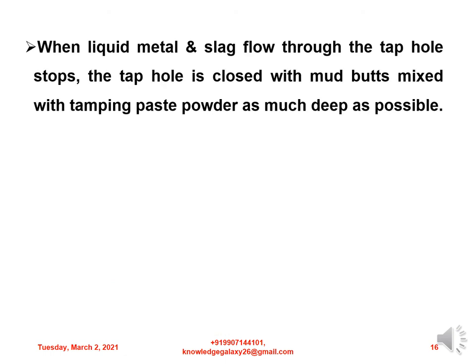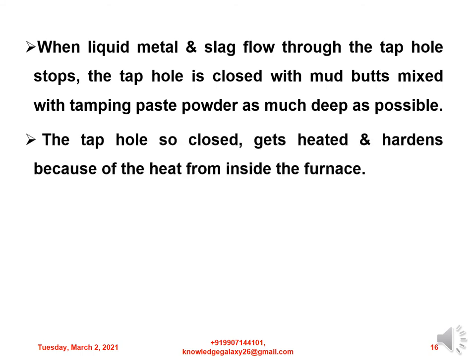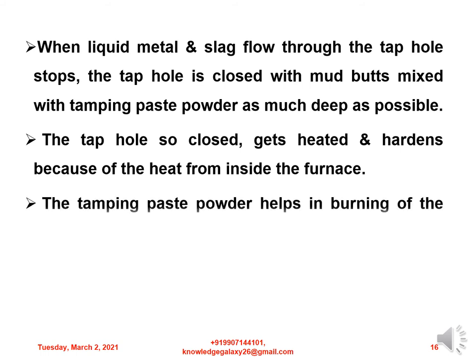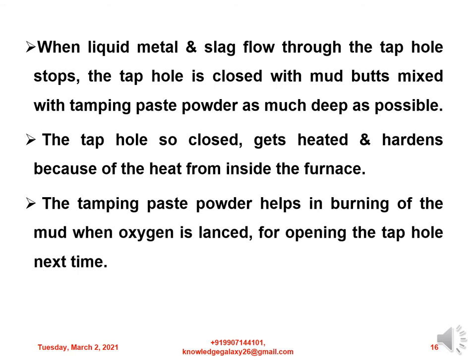When the liquid metal and slag flow through the tap hole stops, the tap hole is closed with mud butts mixed with tamping paste powder, as deep as possible. The tap hole so closed gets heated and hardens because of the heat from inside the furnace. The tamping paste powder helps in burning of the mud when oxygen is lanced for opening of the tap hole next time.